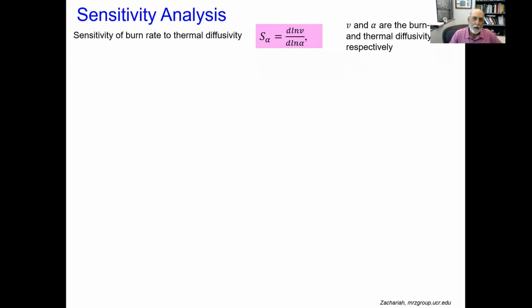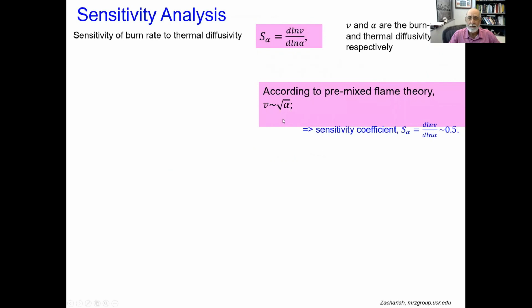So we can now ask things like sensitivity analysis. How sensitive is it to the thermal diffusivity, for example? That's an important parameter when you think that, if you think about premixed flame theory, velocity should be proportional to the square root of thermal diffusivity. We can compute the sensitivity coefficient from this model, the log of the velocity versus the thermal diffusivity, which should be 0.5 by theory.